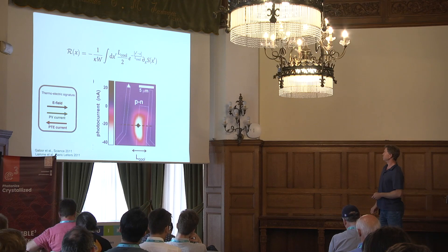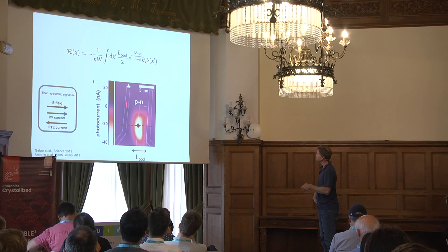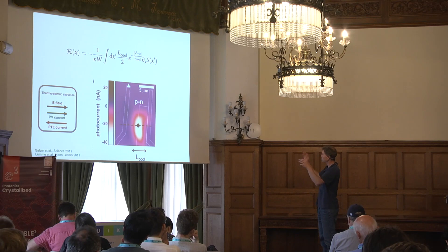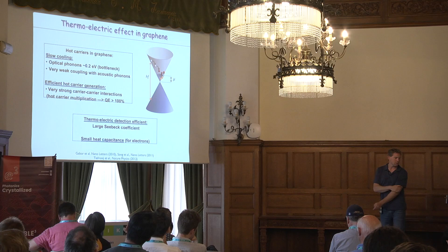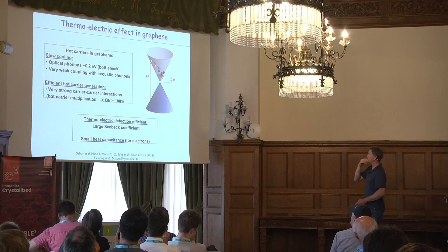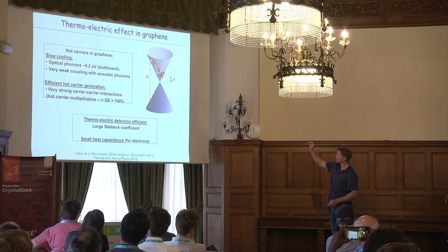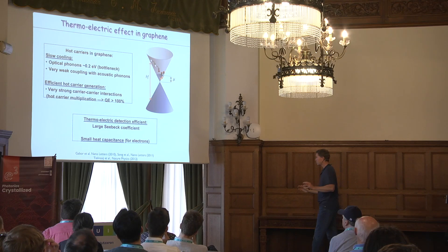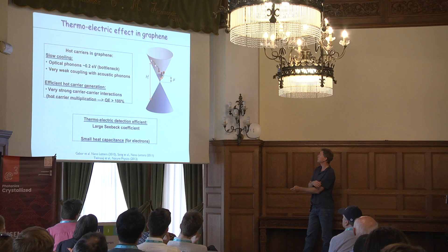The cooling length enters the equation used to calculate spatial profiles of the photocurrent. In graphene, the photothermoelectric effect is strong not only because the Seebeck coefficient is large, but also because the coupling between electrons and phonons is very weak. That means electrons get relatively hot, and that's why photocurrent nanoscopy works so well. We started doing this in 2016 on CVD graphene.